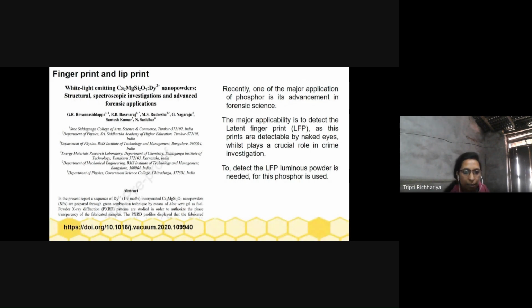Generally, the phosphor materials used for the powder dusting technique can be prepared by the sol-gel method or the auto combustion method. Where the fingerprint is observed, the powder is spread over the fingerprint and the extra powder is blown off, so that the nano powder sticks to the sweat pores of the fingerprint available on that surface. Now that surface is exposed under UV radiation, so the phosphor material glows, and with the help of this, we can easily detect the latent fingerprint of that person and find the culprit.